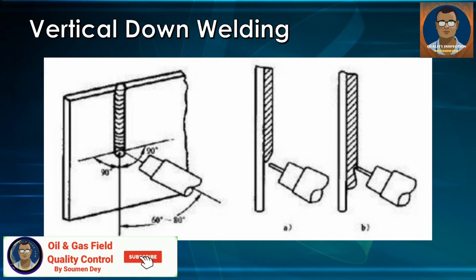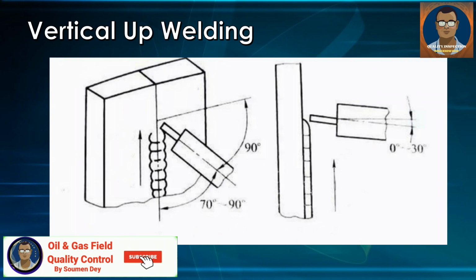Vertical down pipe welding with cellulosic electrodes like E6010 is generally achieved with high welding currents and travel speeds. The welding method is economical and fast, which is why many cross-country pipelines are welded with a vertical down progression using cellulosic electrodes. Vertical up welding is done with lower currents and travel speeds with low hydrogen or cellulosic electrodes. This results in a lower number of beads with larger dimensions. The low hydrogen rods for vertical up progression can achieve welds with almost no slag entrapment and porosity, making them the best choice when rigorous radiographic tests must be passed.